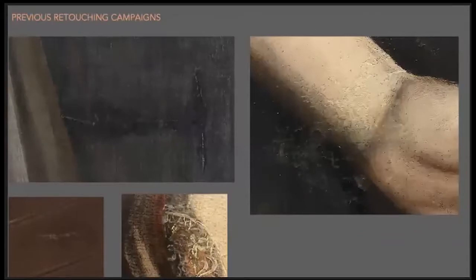As mentioned with problematic wax linings, unfortunately, previous interventions don't always age sympathetically. Aesthetic issues include mismatched or discolored retouching and fills that covered original paint and are texturally distracting. The overpaint and fills in these areas would need to be removed during the cleaning process to allow us conservators to properly fill them and reintegrate them with reversible retouching so they match the surrounding paint film.